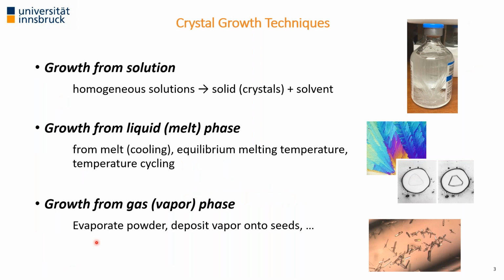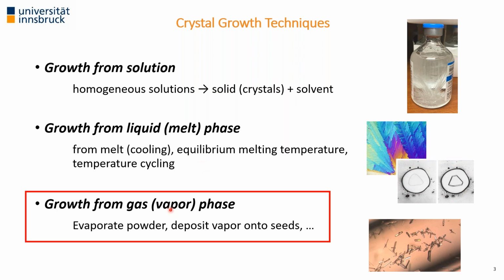So how can we grow crystals? Can we grow perfect single crystals? I would say the most common technique still is growing them from solution. We start from a homogeneous solution, then hopefully end up with some really nice crystals. The second technique is to grow from liquid, from melt, where we can use the equilibrium temperature to grow single crystals, temperature cycling. But the topic of this presentation will be growth from the vapor phase, where we simply evaporate the powder and make sure that we can deposit the vapor onto either a glass or onto seeds.